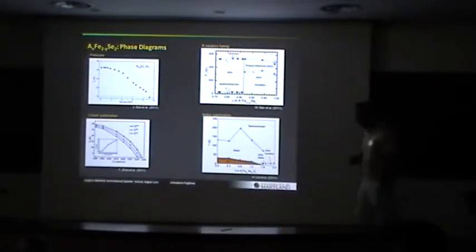But then I think you have to consider how much scattering is going on. If you actually normalize the scattering rate, it may all look the same, in the sense that you're introducing more disorder. How sensitive is TC to that? I don't know that has been measured, because it seems to be so flat. At least for potassium content, it's insensitive.